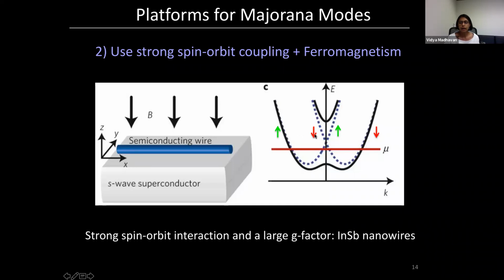And the spin character of these bands looks like this. Now let's turn on magnetism, right? And when you do that, you create a gap right at this crossing point, and you get these solid bands. And now if you can put your Fermi energy inside this gap that you've created, then you're in a situation where there's only one band crossing the Fermi energy. You've completely gotten rid of this other band.